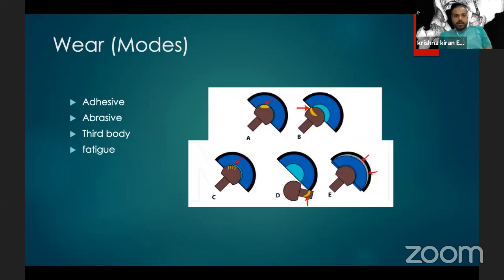The other important tribological principle which we must have in mind is the various methods of wear. So you have 4 primary wear modalities. You have adhesive wear, which happens between the primary bearing materials. So if you have a metal head articulating with a polyethylene, the harder surface will preferentially remove part of the softer surface. That will happen with weight bearing all the time.